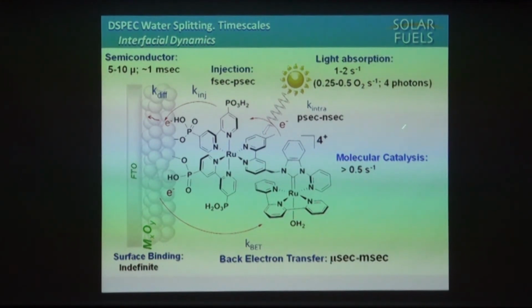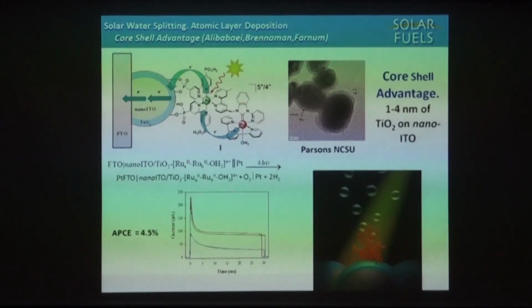What that means is that for every photon that goes in, if you look at these numbers, one photon gives an excitation event, that's great, injection, yep. But 999 out of 1,000 times, the electron drifts back. And so we have back electron transfer. So we're in big trouble. This whole thing, if you look at these numbers and think about the dynamics, cannot work unless you do something else.